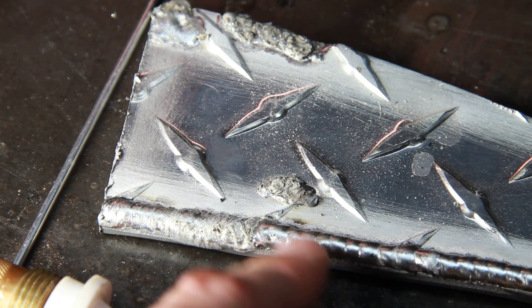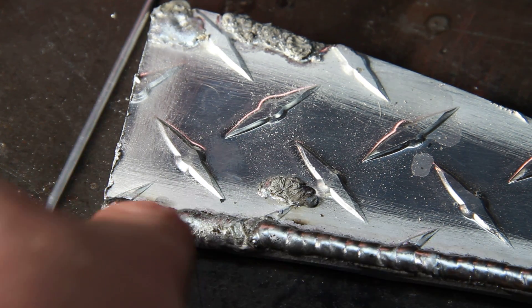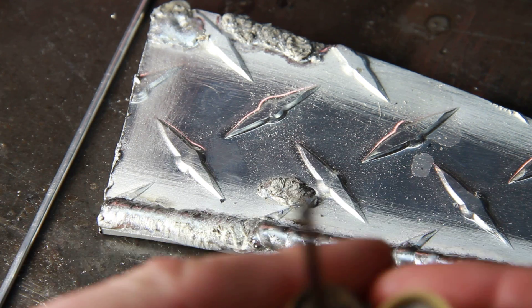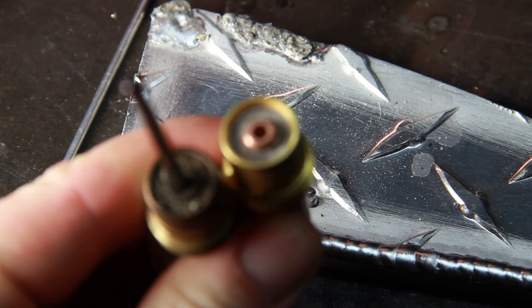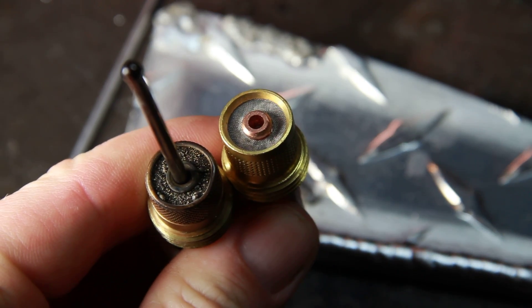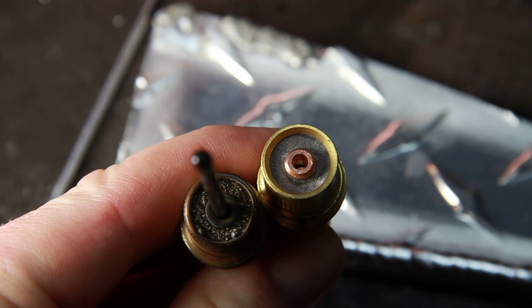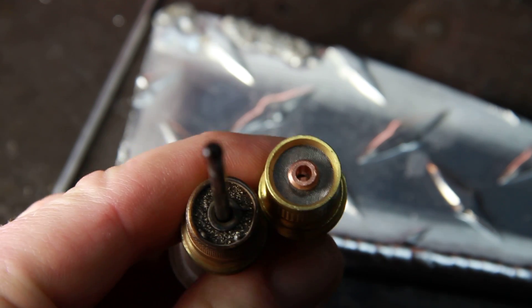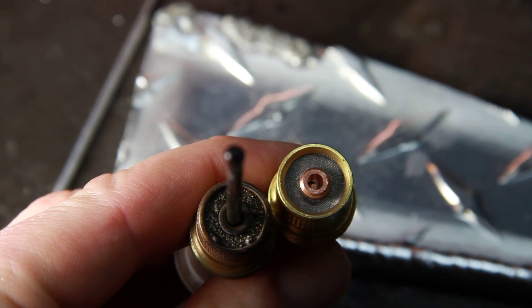Just to a decent looking bead, and I thought, huh, and so I went back, and sure enough, all the exact same machine parameters, exact same gas flow does that, only difference being the different diffuser there.